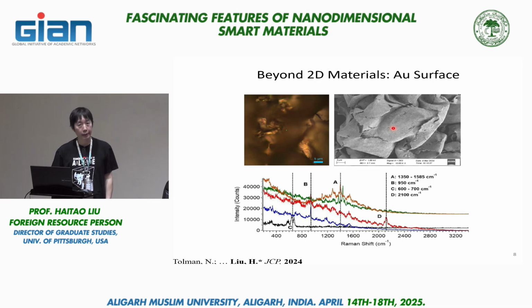This is a very popular analytical technique capable of detecting a single molecule in some cases. So there's a lot of interesting reports within the SERS community about detecting single molecule, or what they claim to be a single molecule event. But when we look at those SERS substrates, in this case made of porous gold, we find that simply by exposing those surface materials to air, we produce SERS signal. And this is good in the sense that it gives us a way to characterize what kind of airborne hydrocarbons are there. So on the bottom, I show some of the representative images and Raman spectra we collected on those SERS substrates. You see some interesting features.